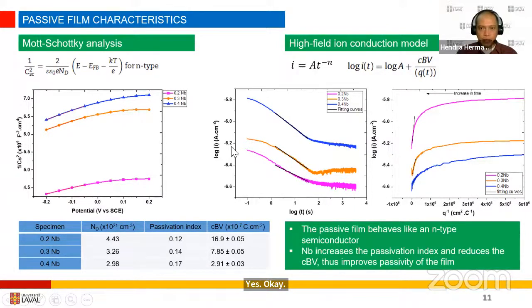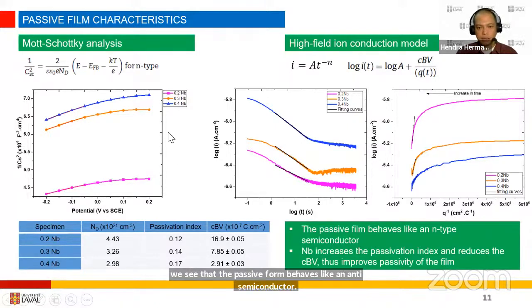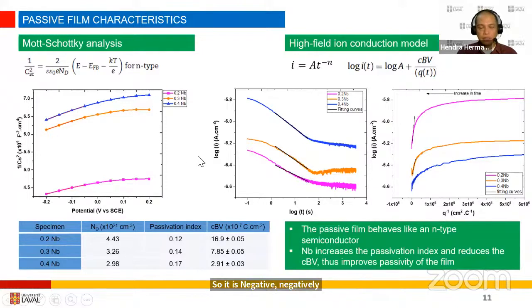And then we use the high field ion conduction model to find out the effect of niobium. Okay, from these two analyses, we see that the passive film behaves like an N-type semiconductor. So it is negatively charged, which is good. So the chloride ion, which is also negative, will not be attracted to the surface. And then niobium increases the passivation index and reduces the CBV.